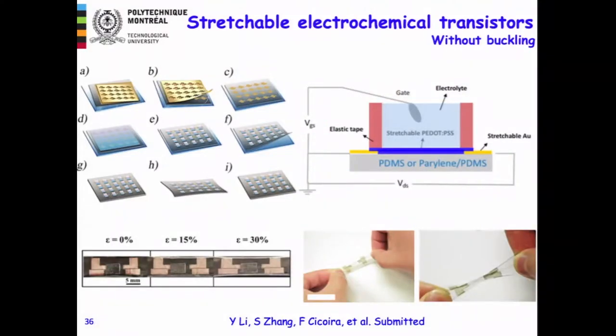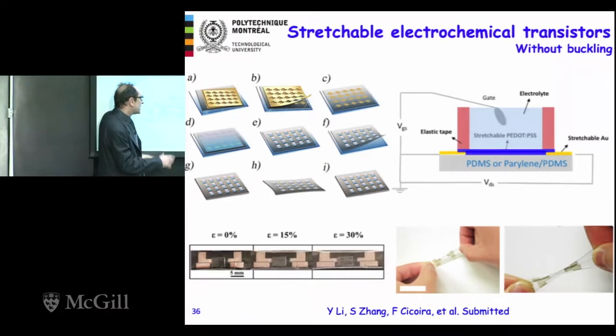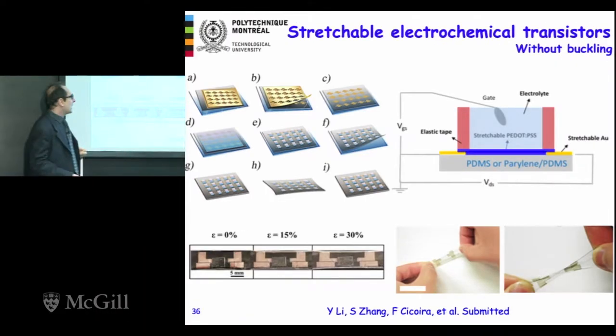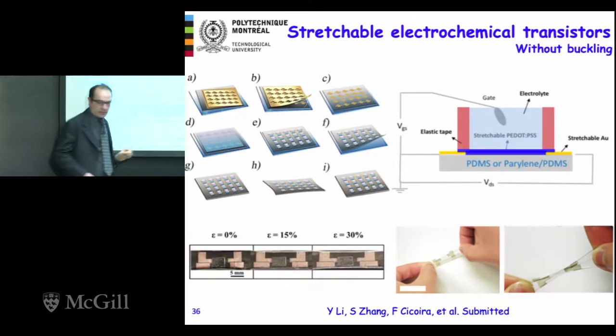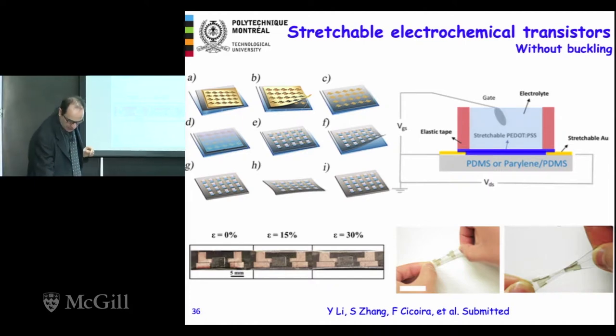And again, very recently, these are some articles under review, we have found a way to make stretchable devices without the buckling system, just by playing with the thickness and the temperature at which we treat this device. So now we can even skip the buckling process, because sometimes you don't want a buckled substrate. If you want something that adheres very well to the skin, for instance, the buckling can disturb. In this case, we can do it without it, and we still have devices that can work up to 30% strain.